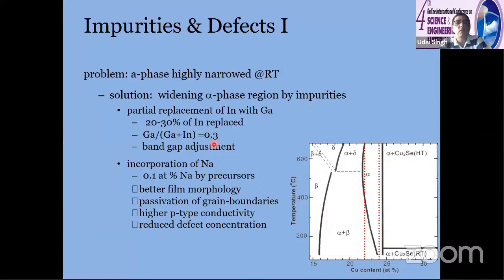But people have seen that if you try partial replacement of indium by gallium, it will slightly widen this, not much. And also the incorporation of sodium into the CIGS film slightly widens this copper concentration range. But you cannot go beyond 24.5. The device will get shorted.